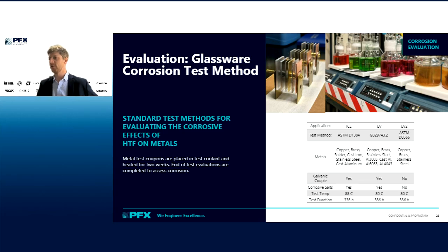And so you'll see some of the differences from the ICE test to the EV tests. As I mentioned, the GB EV test is more severe than the EV ASTM test as it currently stands. And some of the differences that will make things more or less severe, things like galvanic coupling. If you put a metal coupler between two of your metal specimen, this is going to increase the severity of the corrosion test. Corrosive salts is another one that I mentioned.